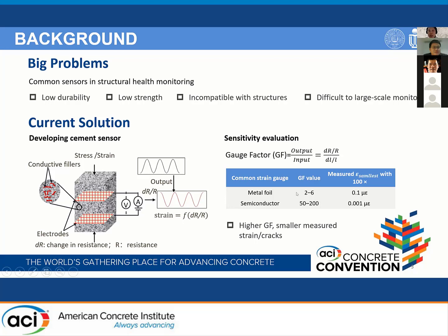For the metal foil strain gauge, gauge factor ranges from 2 to 6. And with this gauge factor value, the smallest strain that the metal foil strain gauge can sense is 0.1 microepsilon after amplification. And for the semiconductor strain gauge, gauge factor ranges from 50 to 200, about 2 orders of magnitude higher than that of the metal foil strain gauge. Therefore, the smallest strain that the semiconductor strain gauge can measure is 0.001 microepsilon after the amplification.